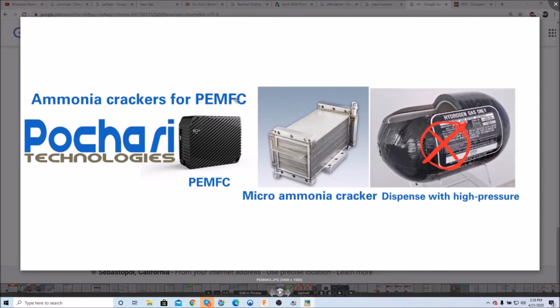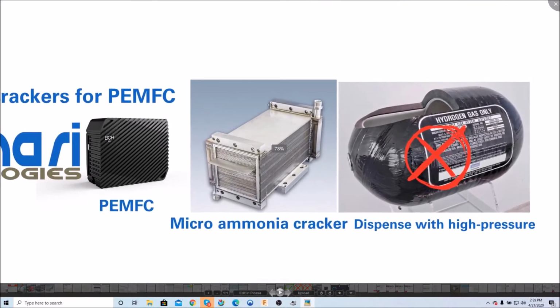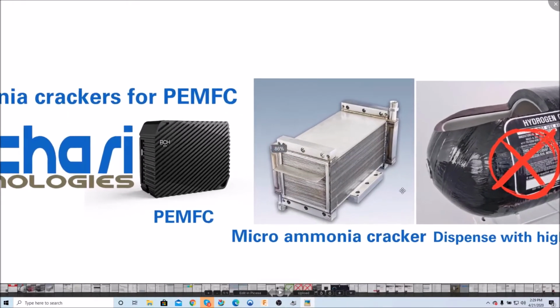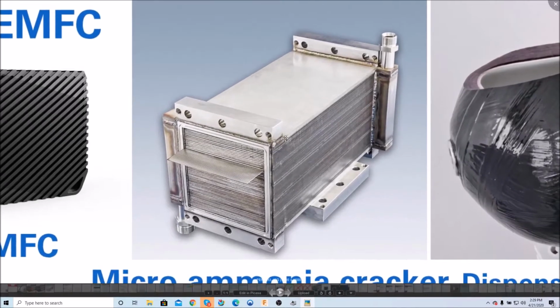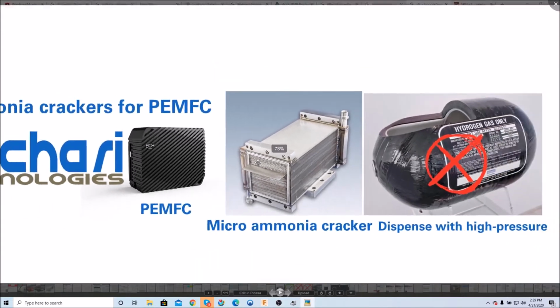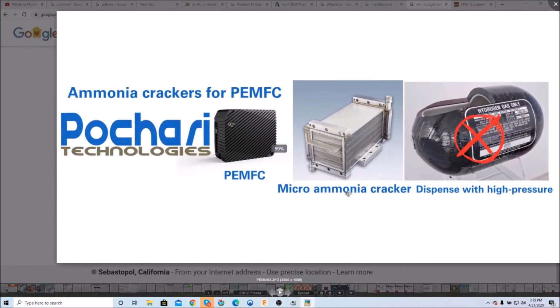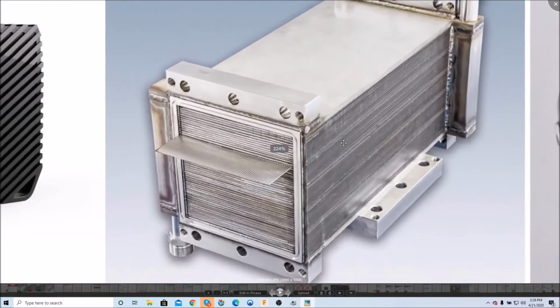This is a cool little marketing thing that I made here. Dispense with high pressure micro ammonia cracker. This is what an ammonia cracker is going to look like. Essentially what you have is this module, and inside this module you have a series of plates that are stacked up upon each other, and between those plates you have a gap, and that gap allows for hot gases to flow through to provide the activation energy, and these catalyst channels are filled using wetness impregnation.